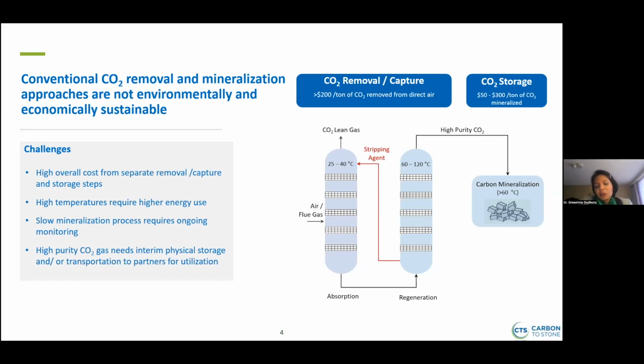So where we're really headed with this is that with CO2 capture technologies, typically we need an absorber with a solvent, and the solvent captures CO2 from a dilute source. The CO2-loaded solvent is then sent into a regeneration column, which typically operates at a slightly higher temperature or a slightly different pressure compared to the absorption column. And this difference in temperature or pressure actually causes the solvent to be regenerated and to be sent back into this absorber column for more CO2 capture.